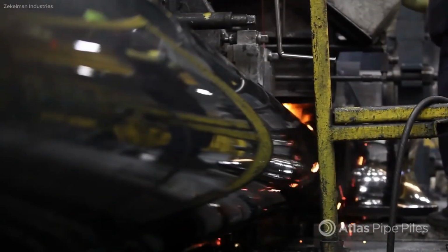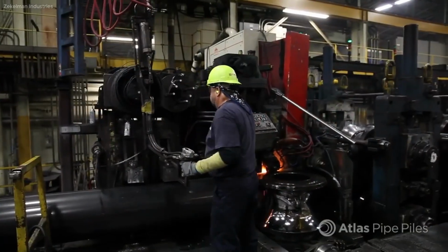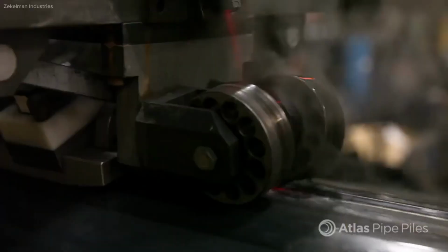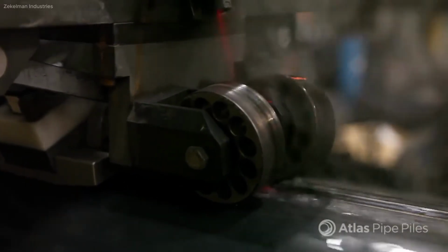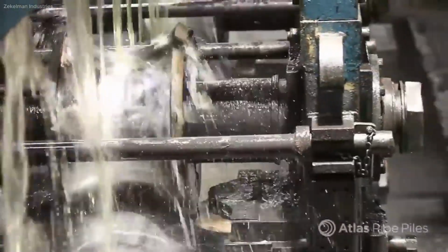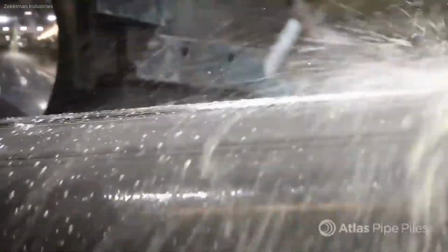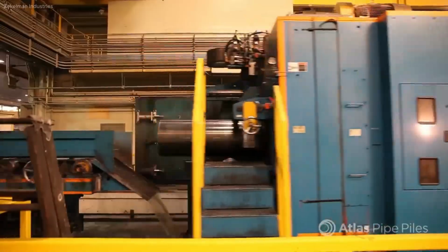Next comes welding, where the edges are fused using electric resistance welding, ERW technology. Copper contact shoes pass a high electrical current through the strip, generating intense heat up to 2,700 degrees Fahrenheit to form a continuous, high-integrity, longitudinal weld.